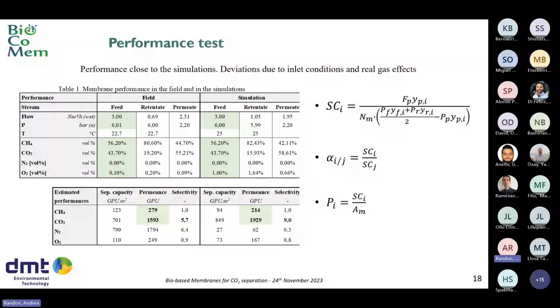So here are some results that they get for this process condition. They sent like 3 normal cubic meters per hour wet feed at a pressure of 6 bars and an almost ambient temperature, 22 degrees C. What they get is a good enrichment on the retentate side of methane because they pass from 56 to 80. And a purity of the CO2 on the permeate side of 55.